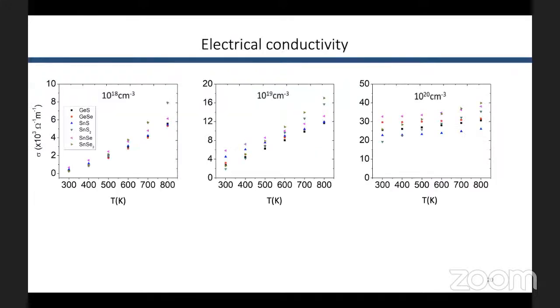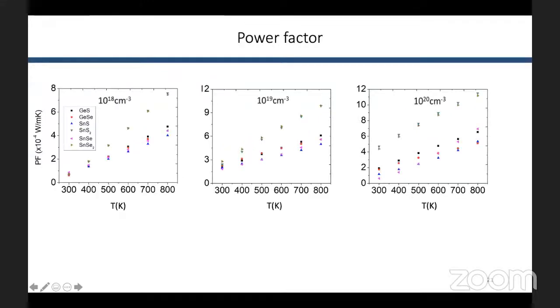Another thing is electrical conductivity, where the electrical conductivity has the same increasing trend for all the materials as a function of temperature. And this is explained as the temperature increases, more electrons are excited, and thus the electrical conductivity increases. We combine both the Seebeck coefficient and the electrical conductivity, and we can calculate power factors.